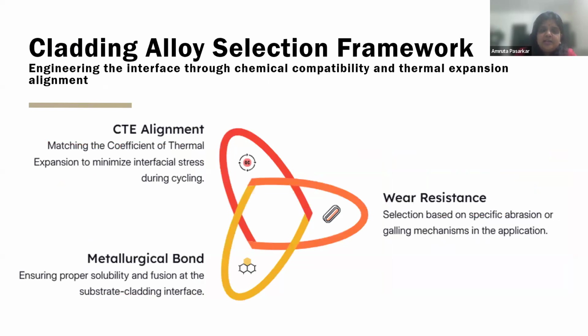Now, how is the cladding done on the base metal? How do we select what material needs to be used for the cladding? First is the coefficient of thermal expansion. What is the coefficient of thermal expansion of the cladding and the base metal? That needs to be checked, because if there is a lot of difference between the thermal expansion coefficients of the cladding and the base metal, then it will cause stresses at the interface of the cladding and the base metal, and it will lead to cracking. So matching the coefficient of thermal expansion of both the materials is very important to reduce the stresses at the interface.